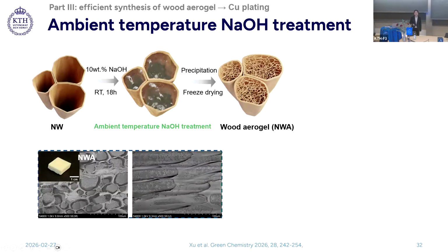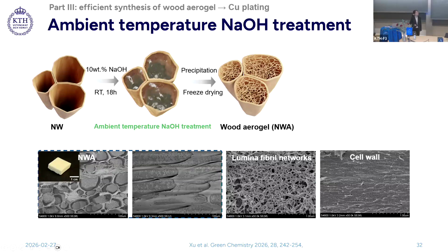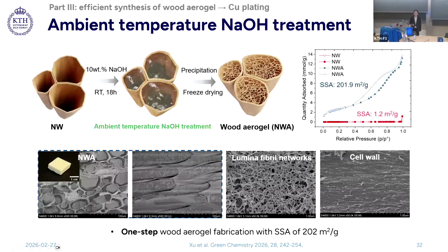SEM images reveal that all the lumen space was occupied with microfibril networks, which can be observed from transverse and tangential planes. In addition to lumina fibril networks, the treatment generates plenty of pores within the cell wall. These two features contribute to a large specific surface area of 202 square meters per gram.